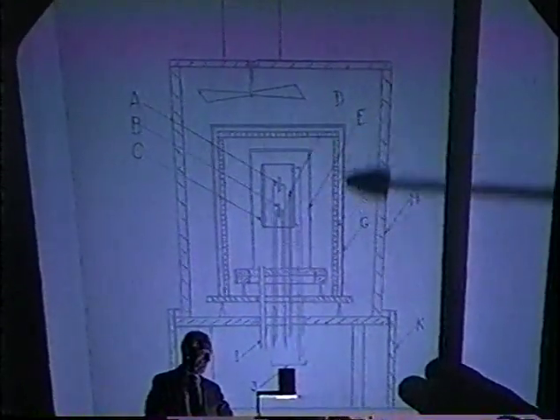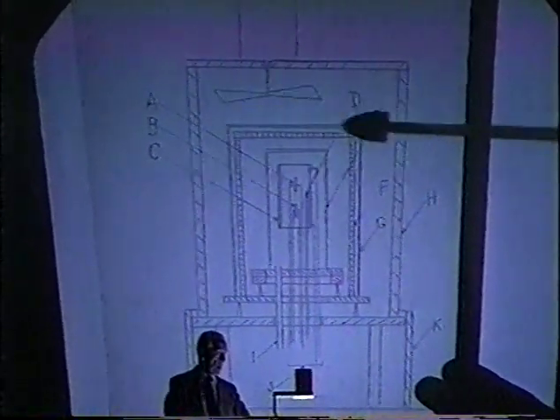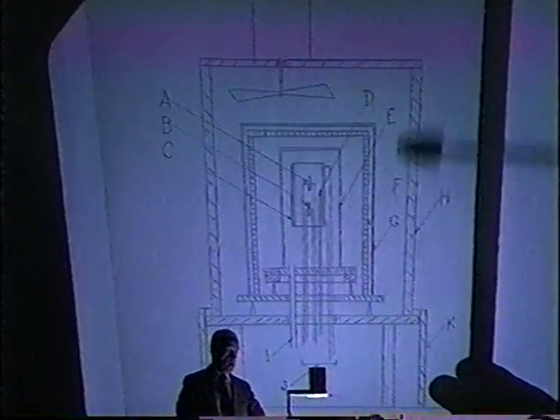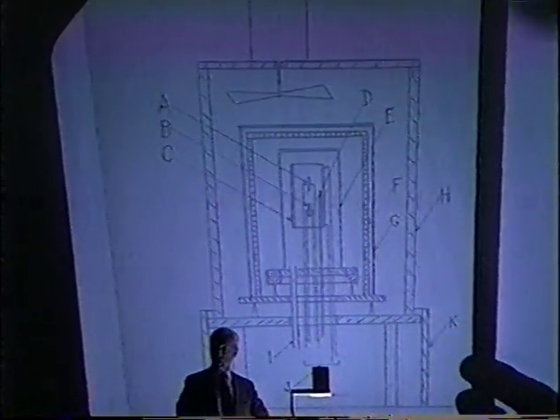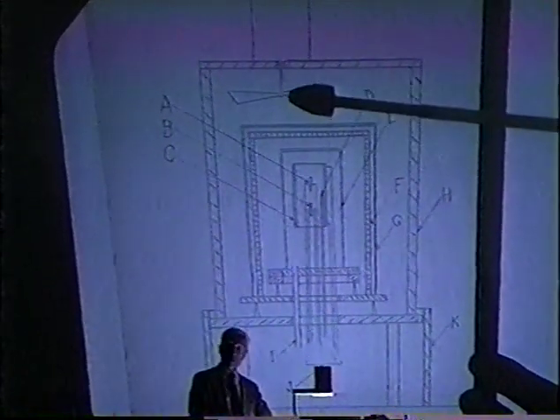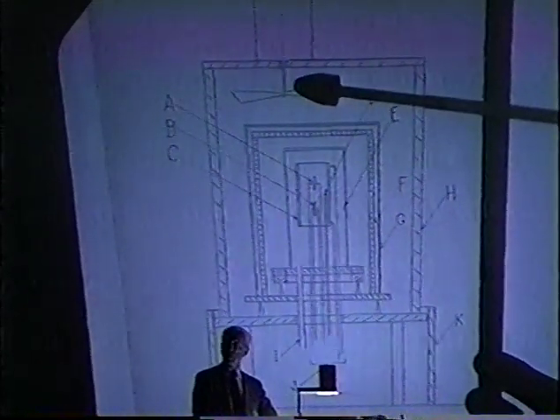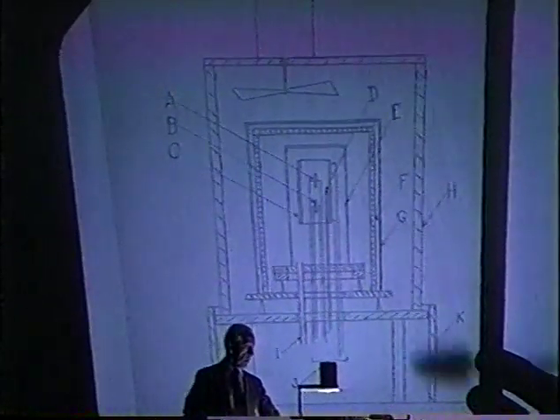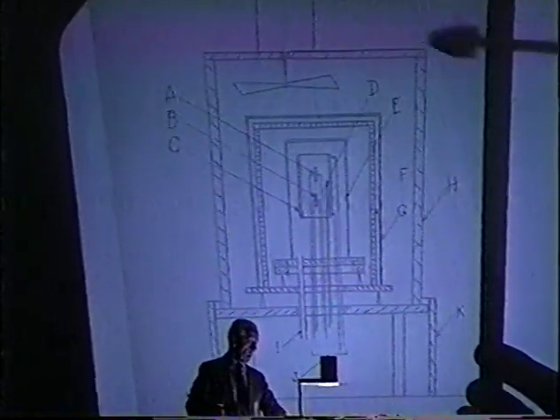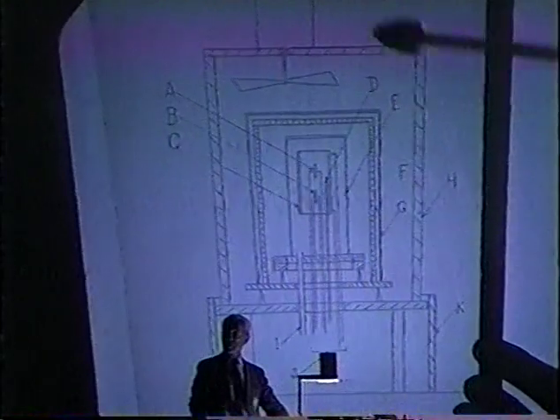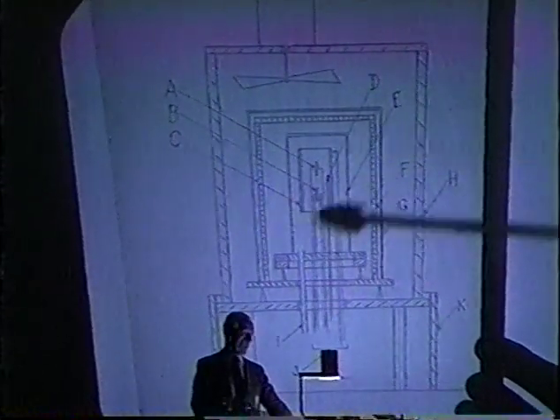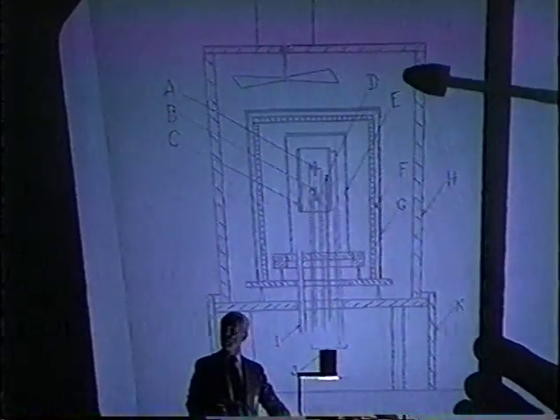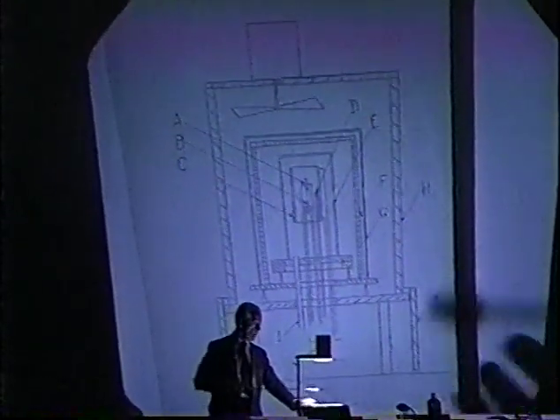The environment of the calorimeter is an air jacket whose temperature is controlled by a separate controller. There is a constant velocity fan to circulate the air, an insulated box, and of course a distributed sensor system and control system to maintain a temperature over here of about 106 degrees Celsius. The heart of this system is, of course, the Seebeck assembly, and I'll show you what that looks like schematically.